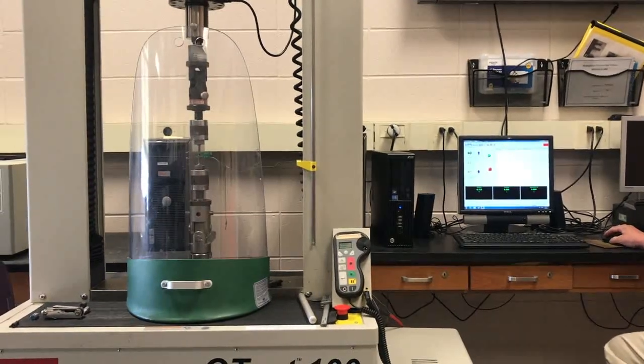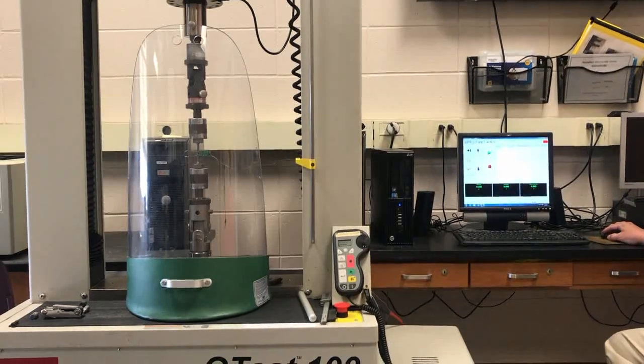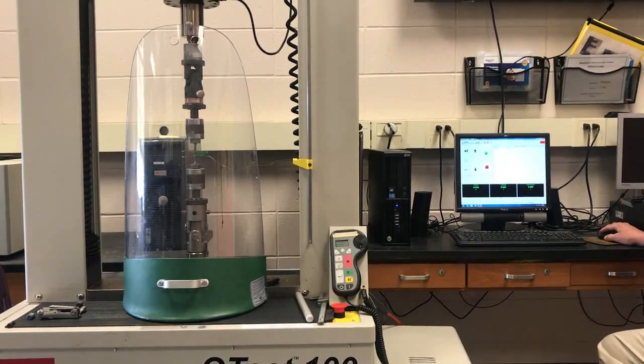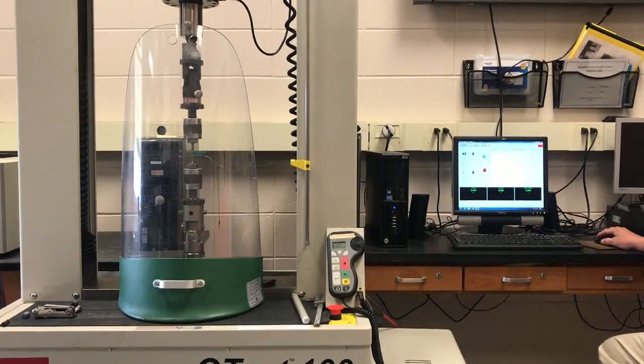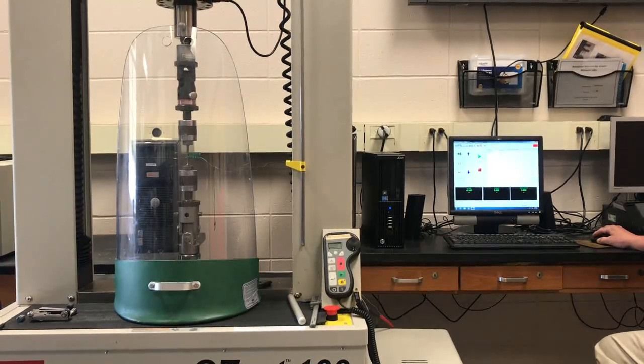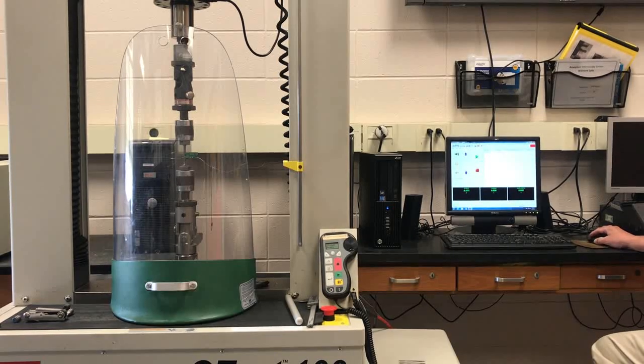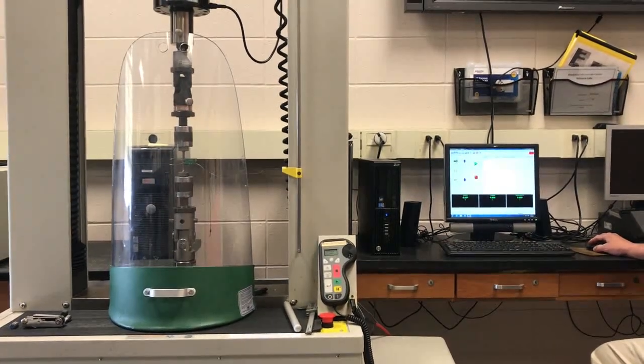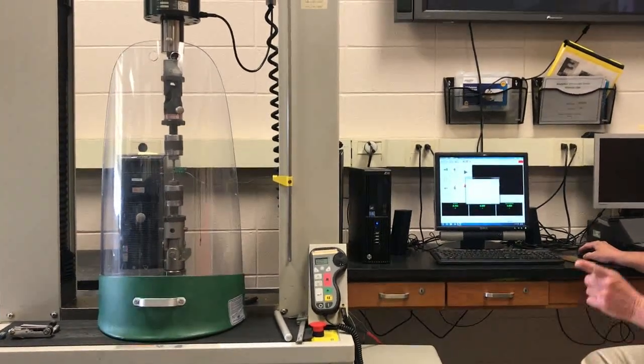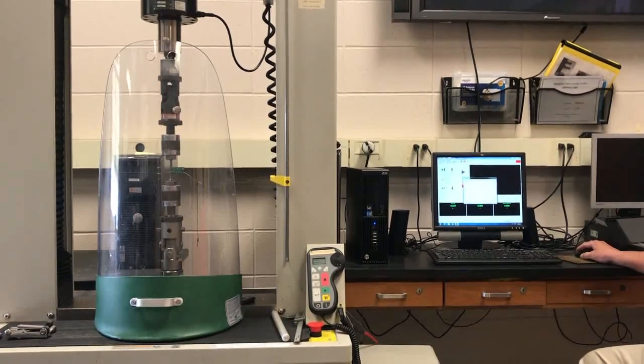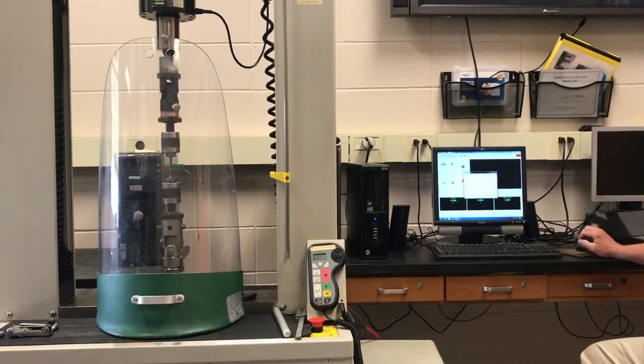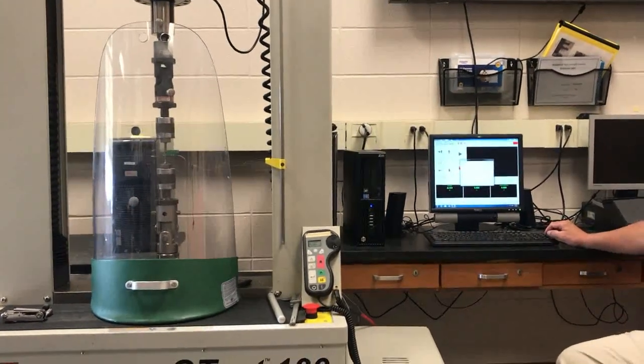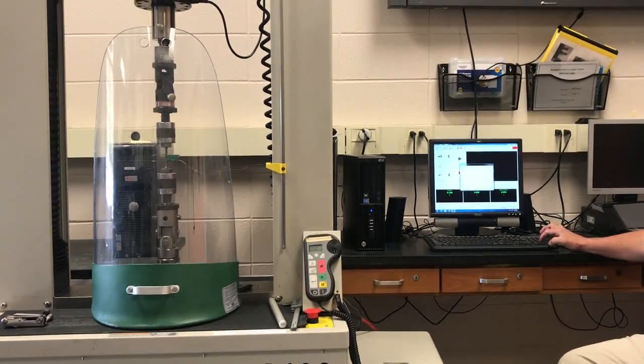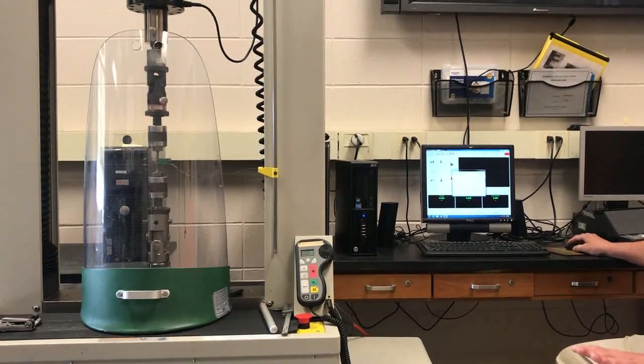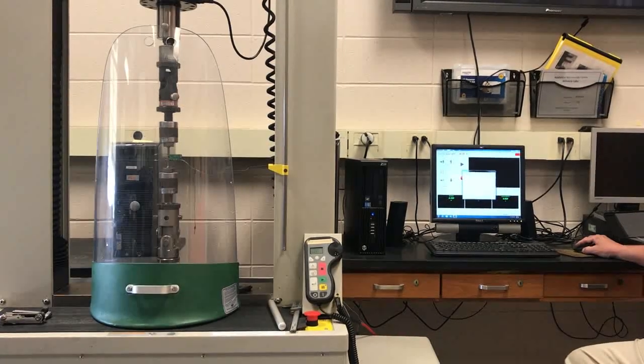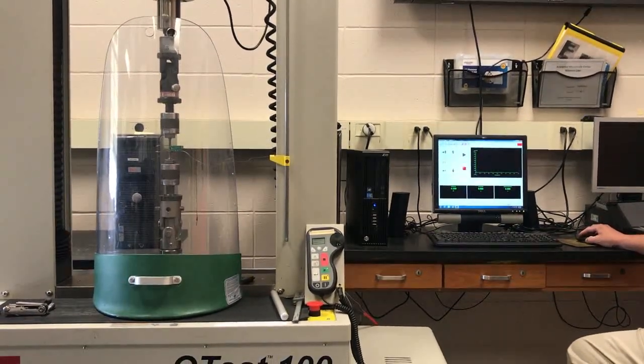About to start the test, you start the test by pressing the green arrow to the right. And again, what you should see is a stress strain curve here. The curve should proceed into the linear portion of the curve, and then before it gets to the yield point, we want to pause the test and remove the extensometer. So, start the test. As we planned it, it's prompting us for the diameter of the sample. So at this point, you want to enter the average value of the diameters you measured earlier here. I'm going to go with 0.238, which is nominal, but you use the average you calculated. Press OK. The test is about to begin. OK. There it goes.